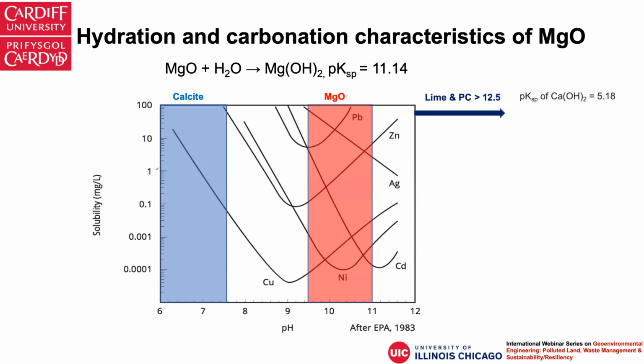And then let's have a look at the hydration and carbonation characteristics of magnesia, because they are related to the magnesia-bearing cements. If we just put this reactive magnesia in water, because it has a very high specific surface area, the dissolution rate is quite high, and it reacts with water readily to produce brucite, or magnesium hydroxide. The magnesium hydroxide, compared to portlandite, the main hydration product of Portland cement, has much lower solubility, almost 6